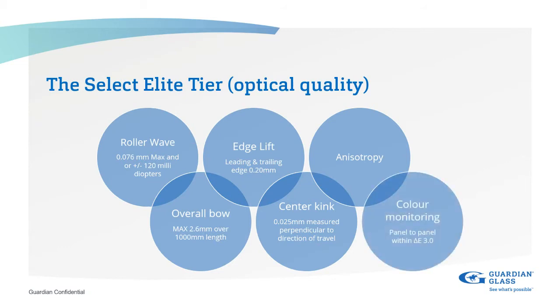And also color monitoring. So this is becoming, again, apparent on some of the projects that I've experienced over the past couple of years, where color monitoring from panel to panel has been a requirement, and it's written into the design document. So part of the Elite Fabricator program is that they must have a spectrometer which can measure the color, the reflected color properties of the glass inside the factory during production, or on the glass as it's glazed at site, so they can measure from panel to panel. We are looking to maintain any difference in color between a maximum delta E of 3.